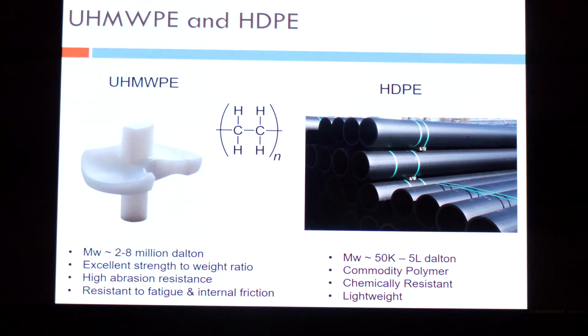So UHMWPE is ultra-high molecular weight polyethylene. And what do I mean by ultra-high? The molecular weights are anywhere between 2 million to 10 million. So very, very high molecular weight, very long polymer chains. In fact, they are so long that you can individually see polymer chains in a transmission electron microscope. They are just very long. They have very high strength. In fact, many hip joints that are used today in surgeries are made out of this ultra-high molecular weight polyethylene. Knee joints are made out of ultra-high molecular weight polyethylene. There are many, many applications of this wonderful polymer because they have very high abrasion resistance.